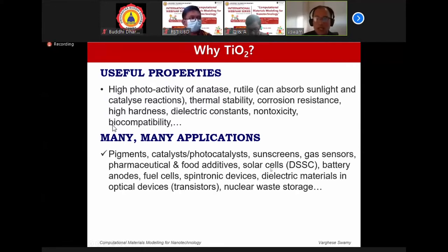we commonly use. Solar cells, that's where the nanostructured titanium dioxide comes in, particularly the anatase phase. In fact, the dye-sensitized solar cell by O'Regan and Gratzel was based on, actually the efficiency of the solar cell was improved a lot when they used nanostructured anatase on which the dye was coated, and the dye was absorbing sunlight and pumping the electrons into the solar cell. TiO2 phases have also been considered as anode materials in fuel cells and many, many applications.